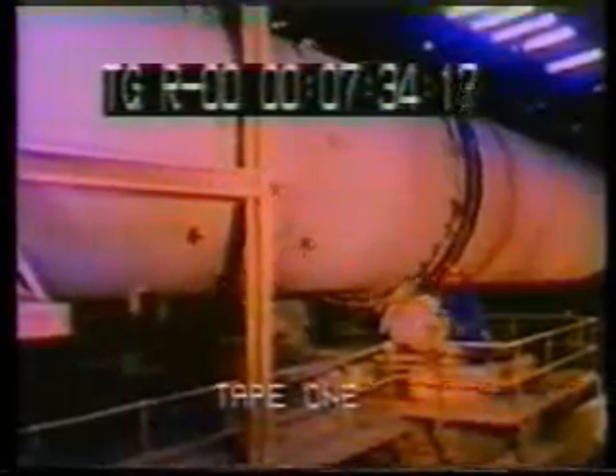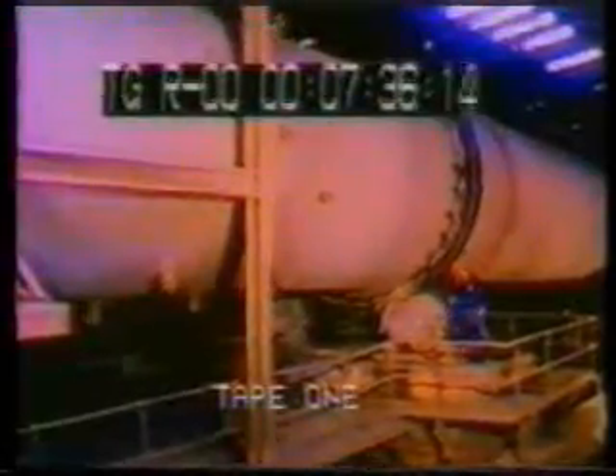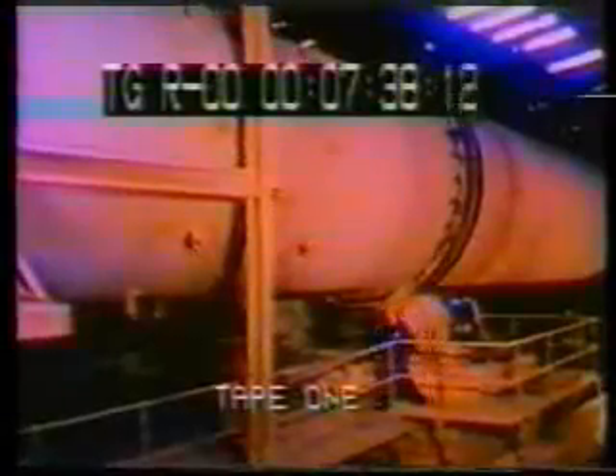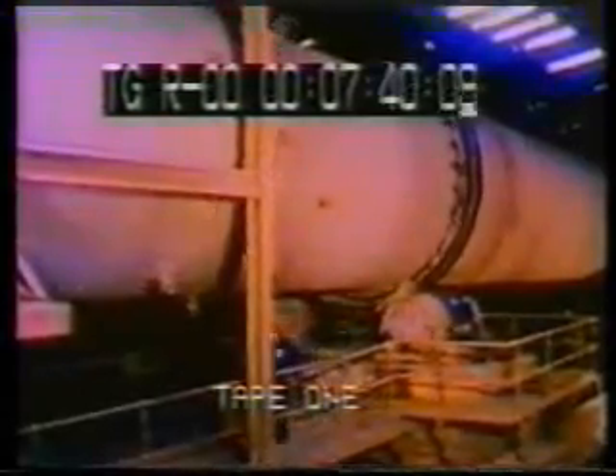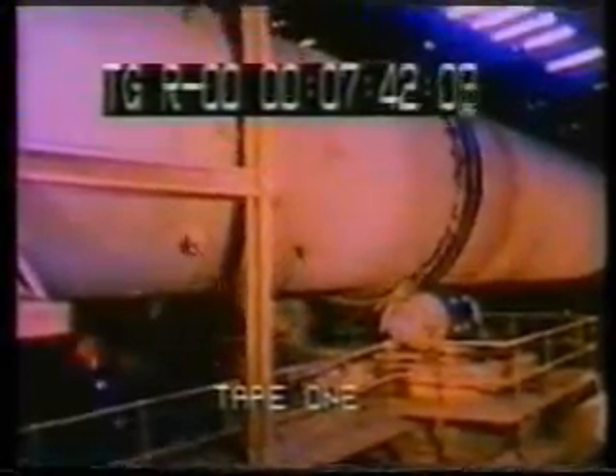Six rotary kilns are employed in the final high-temperature sintering to produce a range of refractory magnesia products. The kilns are oil-fired and operate at temperatures up to 2000 degrees centigrade. The plant's largest kiln is 76 meters long with a throughput of 250 tons per day.